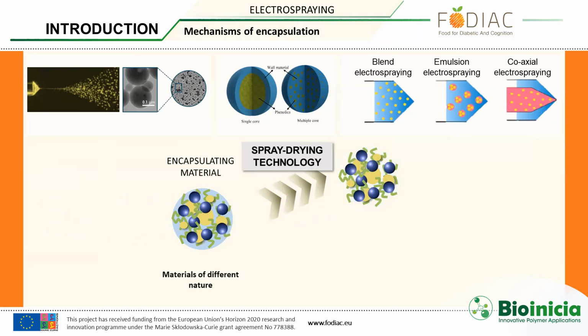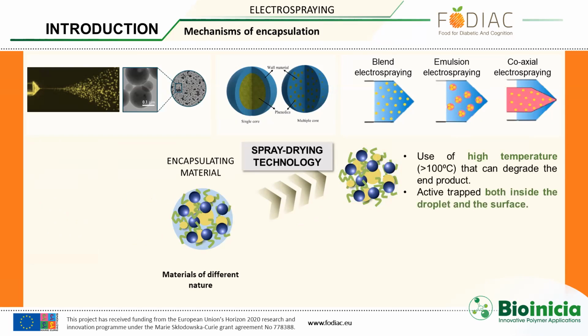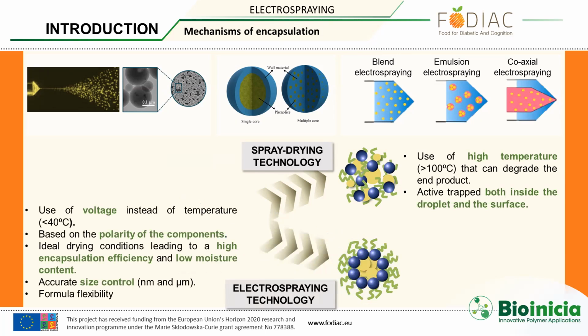If we compare the technologies, for example, spray drying uses high temperature, and the bioactive is homogeneously distributed in the particles, so it can also be on the surface. However, when we encapsulate through electrospraying, we use voltage first to generate small droplets that can dry at room temperature, and the use of the voltage also allows the components of the solution to reorganize based on the polarity and the molecular weight. And normally it's the polymer that ends up on the surface of the particle, so we are getting better encapsulation efficiencies.